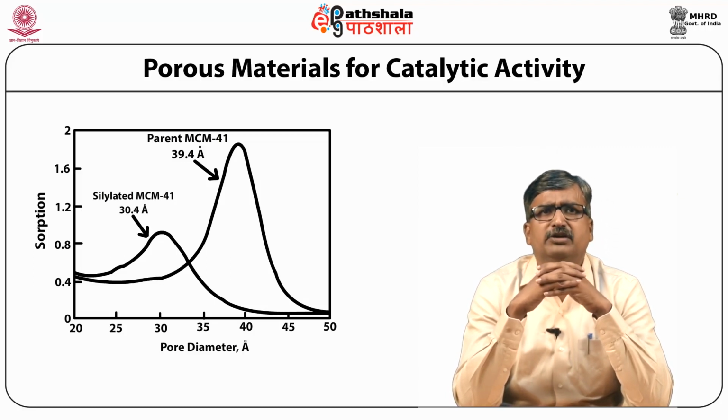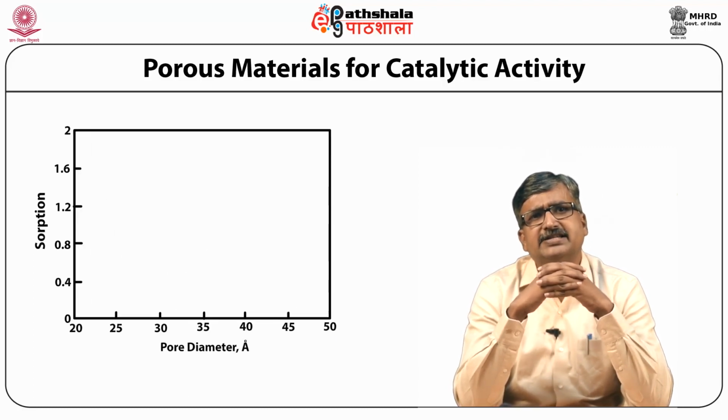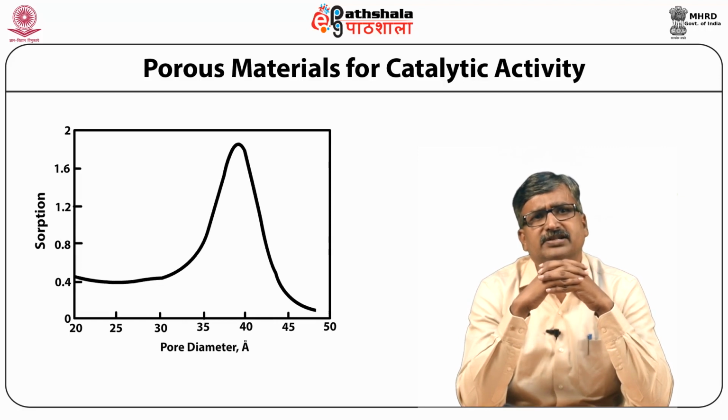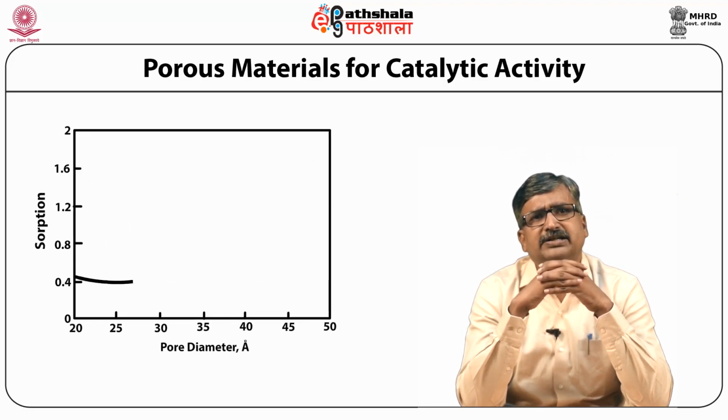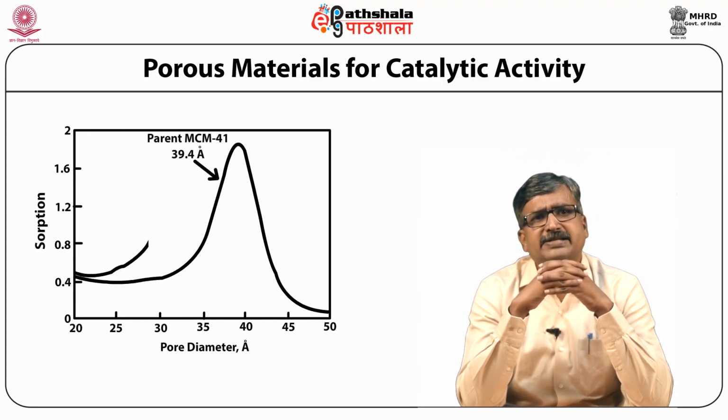Ordinarily, a heterogeneous catalyst consists of a high surface area material that serves as a catalyst support or substrate, and the surface lining of its pores contains a dispersed active component, such as an acid site or platinum atom, which brings about the accelerated catalytic reaction. Examples of the substrate are the oxides silica, gamma alumina, titania in the tetragonal anatase phase, and zirconia. Mixed oxides are also in common use, such as high surface area silica alumina.